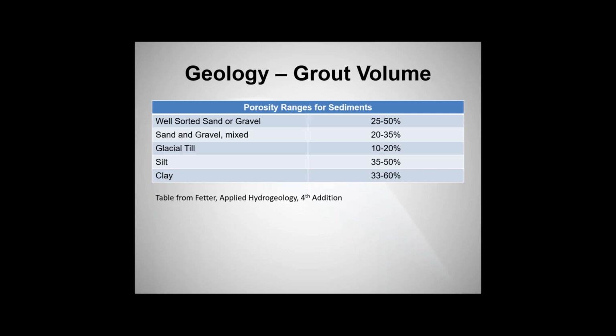Sand and gravel mixed is lower simply because you have different grain sizes, so they fill in those spaces. Glacial till, lower along the same principle. But then you get into silts and clays, and actually silts and clays have really high amounts of porosity. However, the permeability, hydraulic conductivity, is very low. The grain sizes are so small that it's hard to push a fluid into those.